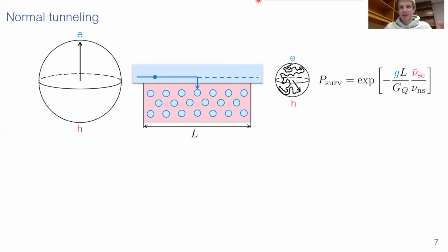However, these normal cores of the vortices create parallel conduction channels. So the electron does not necessarily get to the downstream electrode. It can also tunnel to the normal core of the vortices and get lost there. So there is only some probability with which the electron gets to the downstream electrode, which we call the survival probability. This survival probability is determined by the interface properties and also by the density of states in the superconductor at the Fermi level due to these normal inclusions. This density of states increases with the magnetic field, so this survival probability gets smaller with the increasing magnetic field.